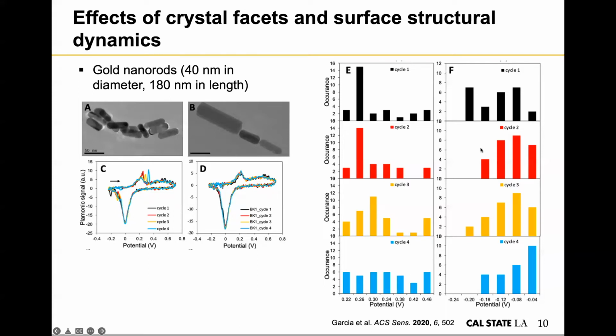And here we show that we surveyed multiple nanoparticles and compared the peak positions from cycle 1 all through cycle 4, and you can see that there is a general drifting from about 0.26 volt to the disappearance of this minor peak around the same potential. And same thing here, we also see some systematic transformation of the minor peak positions during the cycles.